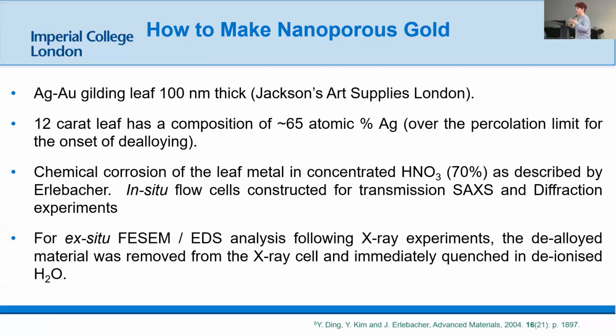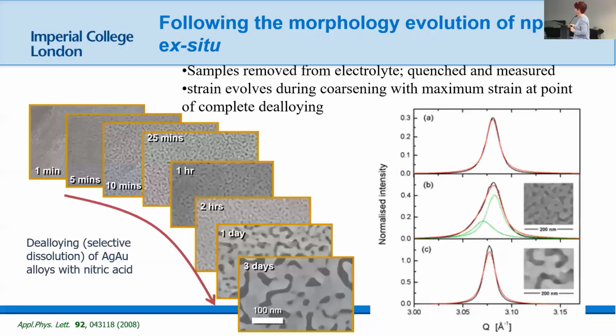I did say there was a critical potential for dealloying. But if you've got a strong enough acid, the open circuit potential is above that critical potential. So you can just float this stuff on a beaker of, I'm making this sound not very impressive, nitric acid, and you will end up with nanoporous gold. So we use this really easy chemical approach, coupled with a really complex advanced synchrotron approach, to study some of these properties.